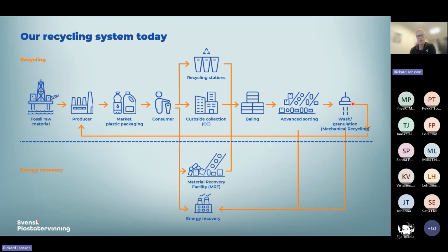and there is not always a market demand for these low quality materials, which means that we cannot always get off-takers. Even if we would sort them into a specific fraction, there is not always an off-taker that would accept these laminated structures, and then we get a sorting reject instead. Or there is technical difficulties when you sort the material. For example, if you have black plastics that contain carbon black as the pigment, the carbon black will interfere with our sorting machine so that we cannot clearly distinguish which plastic type it is, and then we would ignore it instead, and it could potentially end up in a sorting reject that we instead send for energy recovery.